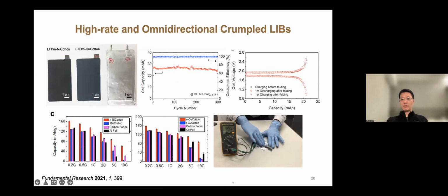So this is the same clip as I showed you at the very beginning, that we can actually fold the cell. And at the same time, you'll see that using our NiCotton, we can actually increase the speed significantly, right? The 10 Cs, we still get around 50% of the capacity of the electrode. And this curve show you that after 1,000 times of bending and not bending, right? The charge and discharge curve will heavily overlap, right? So that means how stable the cell it can be.